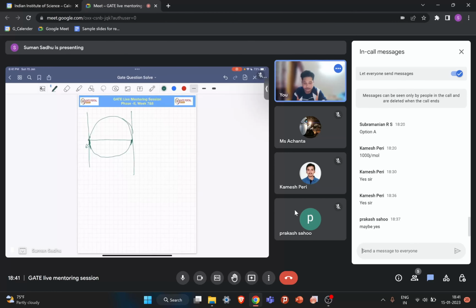Because near your pure elements the slope is minus infinity, always here your free energy will decrease initially. Then when the delta H part dominates the minus T delta S part, it will again increase. Similarly at this end it will also decrease.